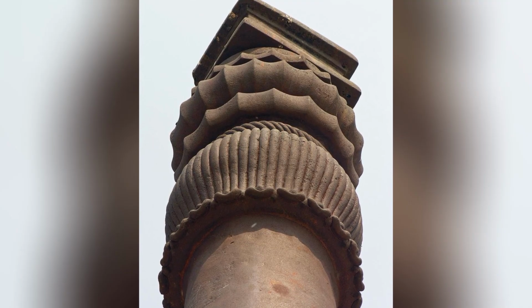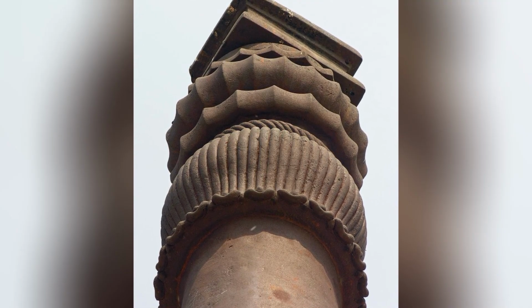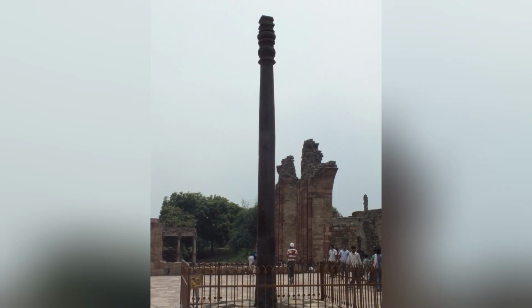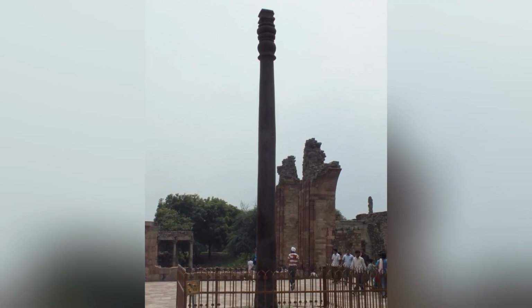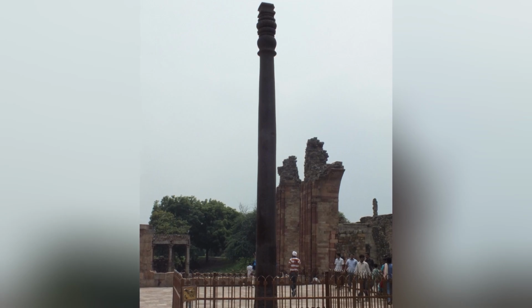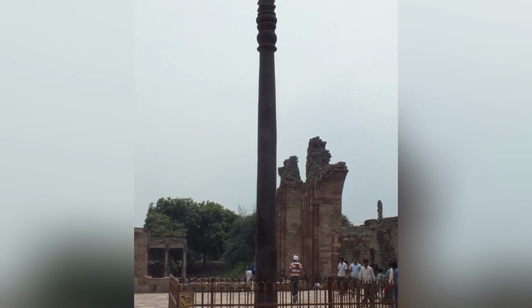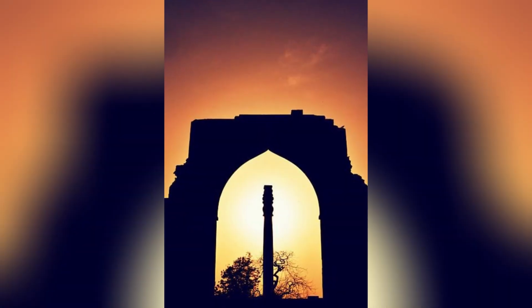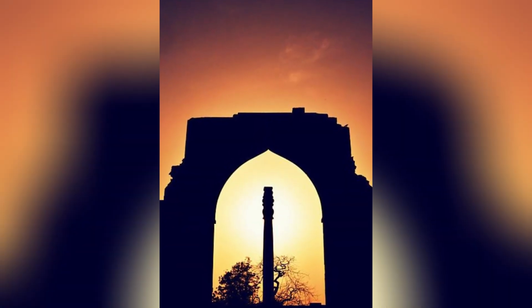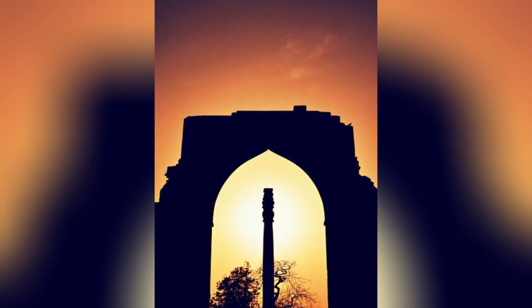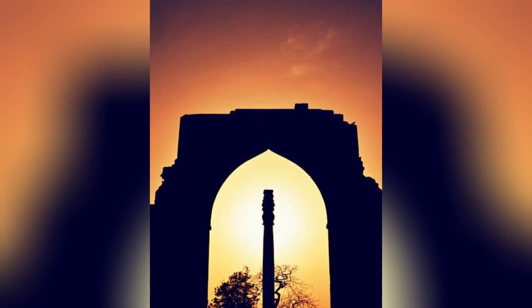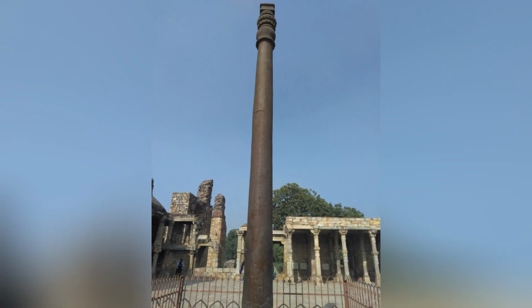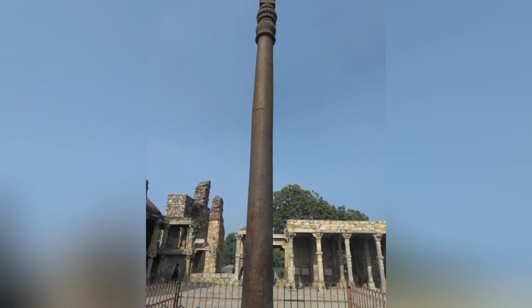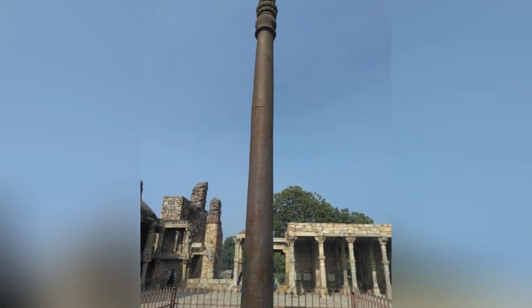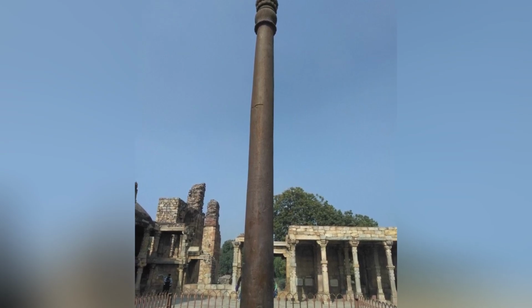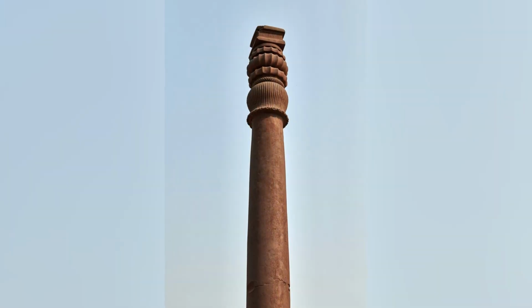The scanning electron microscopy examination of cross-sections of the film has revealed its layered structure with distinct layers that correspond to the annual cycles of wetting and drying that the pillar has experienced. The individual layers, which are typically a few tenths of a micrometer thick, can be counted like the rings of a tree, and the number of layers provides an estimate of the age of the film and of the rate at which it has been growing. The counting of the layers in the film has confirmed that the film has been growing for approximately 1600 years, consistent with the known age of the pillar.